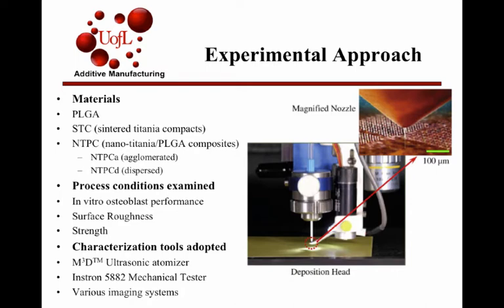As for the process conditions, they did in vitro osteoblast performance. They also did surface roughness measurements and strength testing. For the strength testing, they didn't use the 3D printed parts because those are on the micron scale, but they did use the same material, so they cast it rather than 3D printing. And then they used an M3D ultrasonic atomizer. That's the printer process. And then they added an Instron mechanical tester and lots and lots of imaging software. So they use AFM, SEM, lots of different types. This picture here is an image of the printer. You can see the magnified nozzle that's a 100 micron, that green bar. So it's printing very, very small structures.